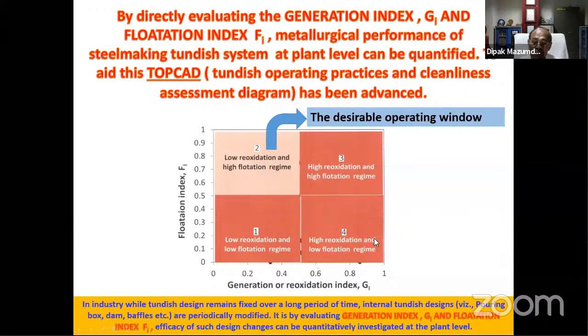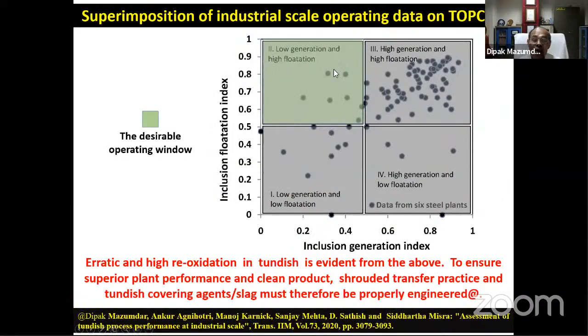And if you now plot the industrial data from Indian steel plants, the figure is alarming. You could see that only a few points fall in box number 2, and the bulk of the points fall in box 3, which is the region of high generation and high flotation. This tells us that the Tundish is not working well as far as reoxidation is concerned. High flotation is there, but high generation is also there. So that means reoxidation is a big problem in the Indian steelmaking system.